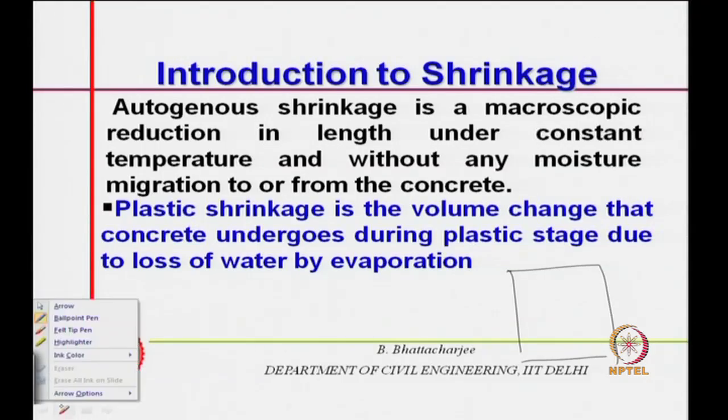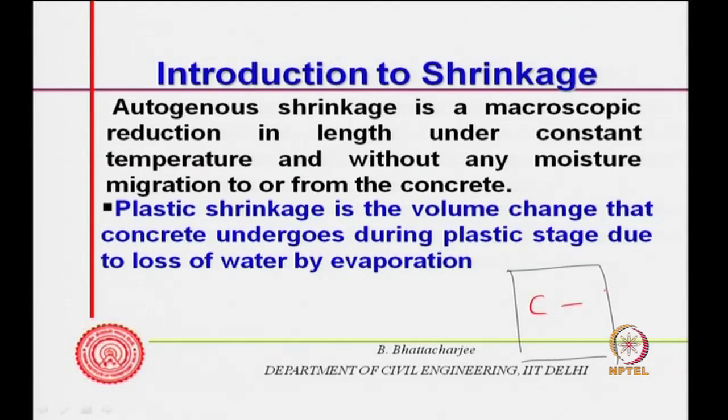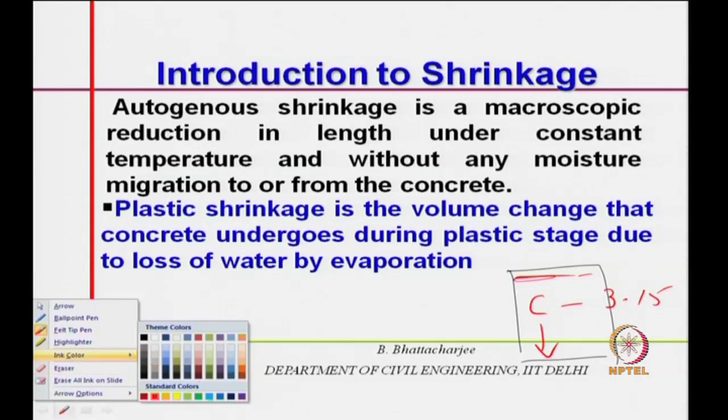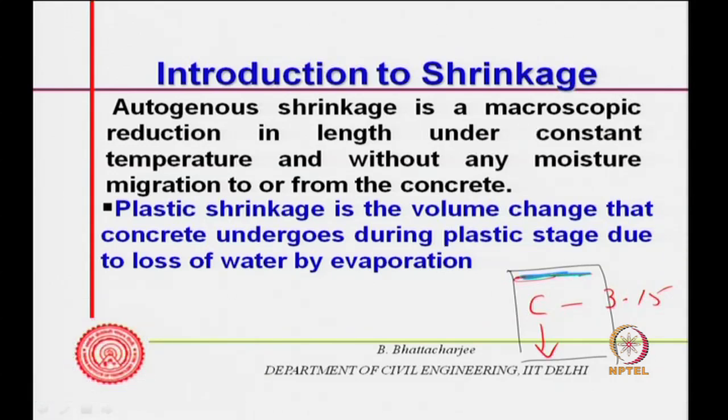So, what you will have is something like this, this is your concrete, and because the specific gravity of cement is 3.15, it will have a tendency to come down and water has a tendency to come up. So, you will have water coming in here and accumulating as bleed water. And if it evaporates, or even if there is no bleed water but some water evaporates from here, more water will tend to move upward and therefore the solid will subside, and settlement would occur. So, there is a volume change associated with this because of loss of water by evaporation, and quite often this is referred to as